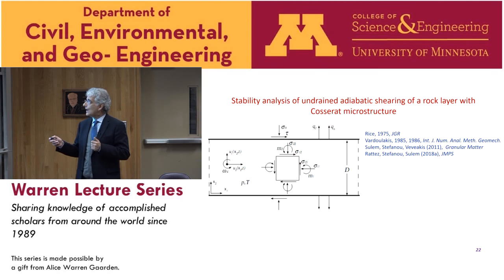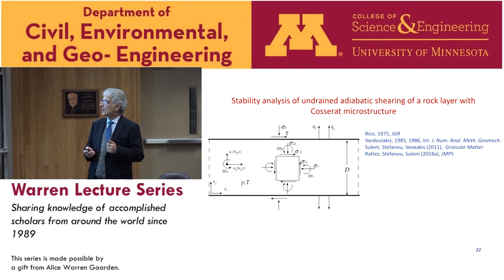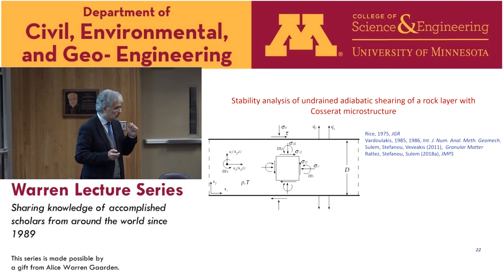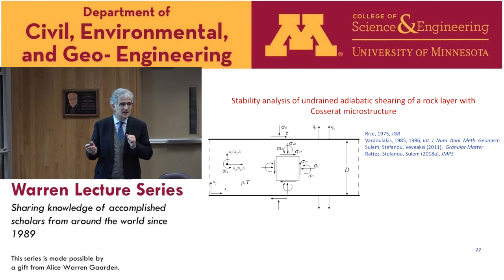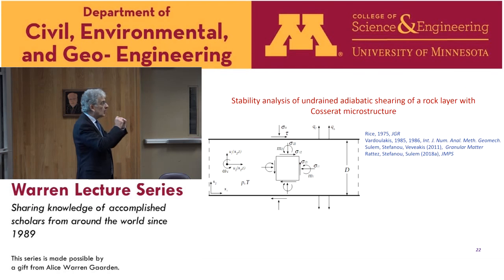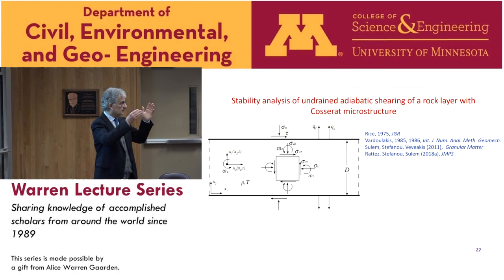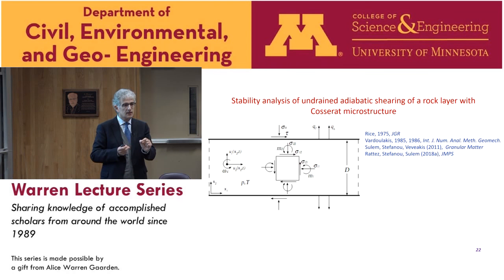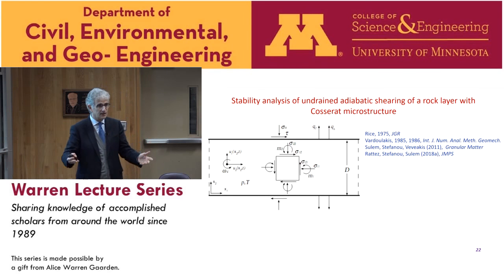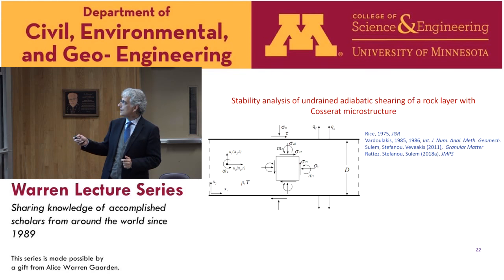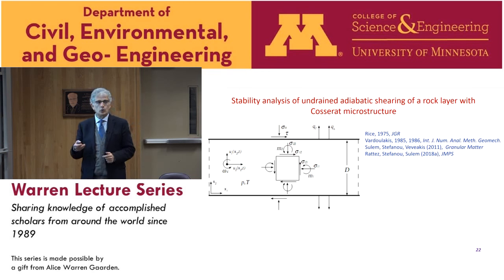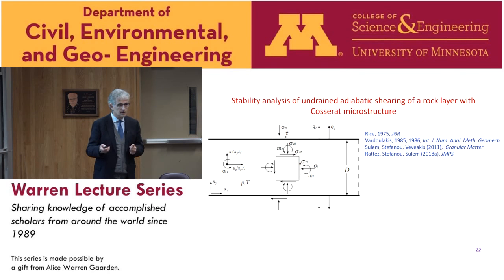However, as discussed by Yanis Vardoulakis a few years after, this mathematical problem is ill-posed because what we find from the stability analysis is that the dominant wavelength of the instability mode is infinitely small. So again, in a classical continuum, everything is localized in a zone of zero thickness, and the rate of growth of the instability in time is also infinite. So this is an indication that there are the conditions for the onset of instability, but we cannot say anything after that. In the paper of Vardoulakis, Yanis introduced the effect of viscous term in order to regularize the system.